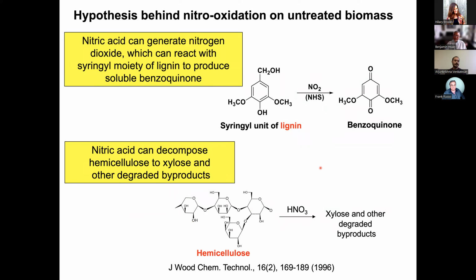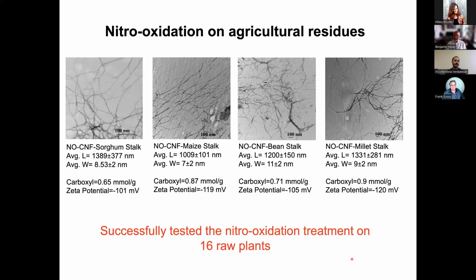And the reason that this chemistry will work very well with the raw biomass, meaning you don't have to pulp them, is because nitrogen dioxide can react with the major components in lignin, like syringyl units, and they become soluble. And also nitric acid can degrade the hemicellulose. So this is all well known for quite some time. We just tried to combine the previous knowledge, and it turned out this nitro-oxidation method can be utilized for any biomass.